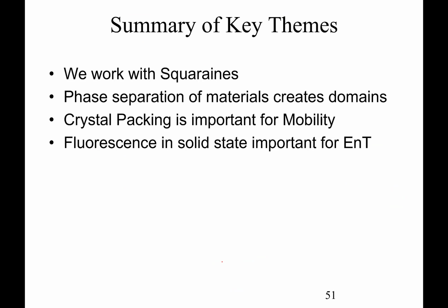So a summary of the key themes so far in the first part of this presentation. Yes, we work with these squaraines. It turns out that phase separation, which we can control by heating up these materials, creates these domains. We don't want the domains to be too large in size. We think that crystal packing is important for mobility, the ability of charges to move. That's conductivity, right? The mobility of charges through the devices. We also think that fluorescence in the solid state may be important for energy transfer. So that's a summary of the key themes so far.